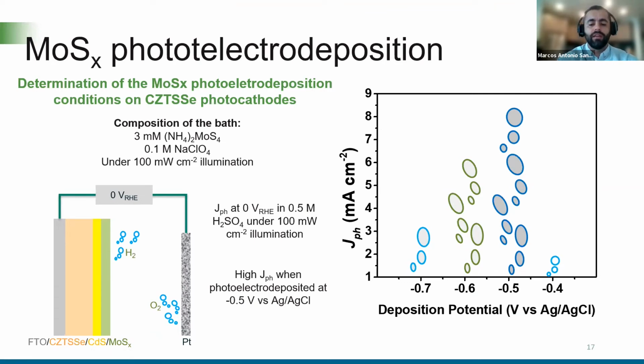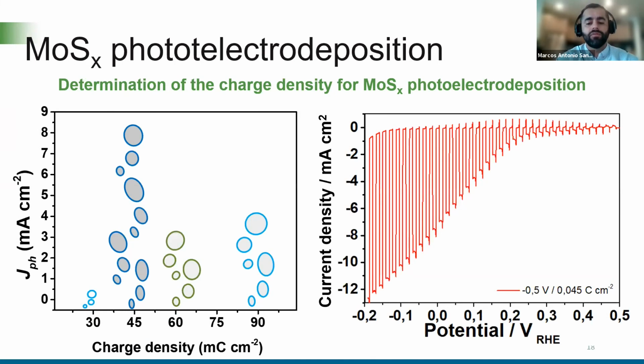Furthermore, we investigated the effect of the amount of molybdenum sulfide deposited by changing the deposition charge density, and we obtained the best results for water reduction when we deposited 45 millicoulombs per square centimeter. When we used high charge densities, we noticed this decrease of the photocurrent. It can be associated with deposition of a thicker molybdenum sulfide layer that can cause a decrease of the absorption.